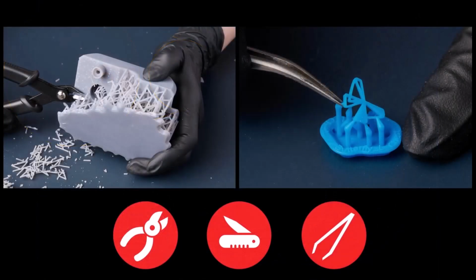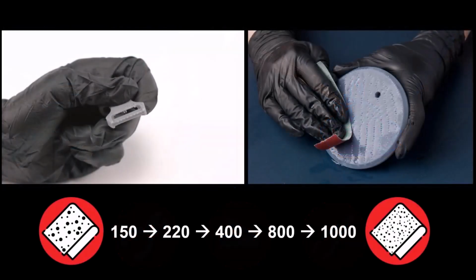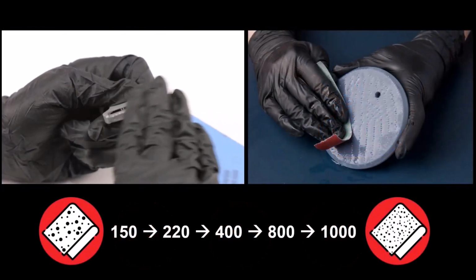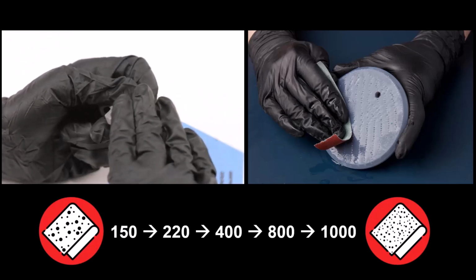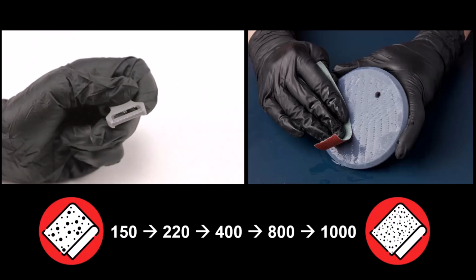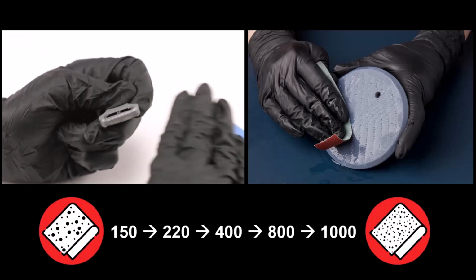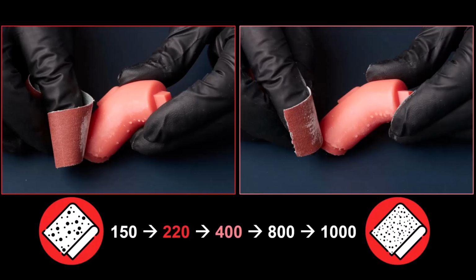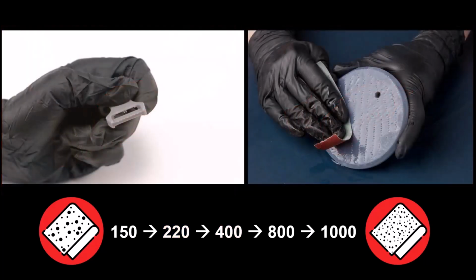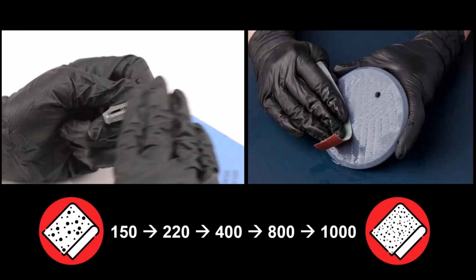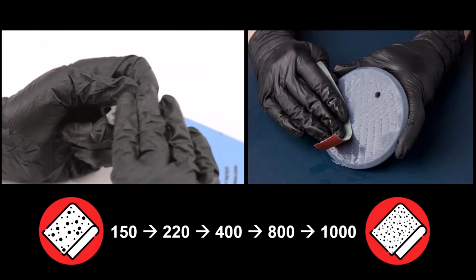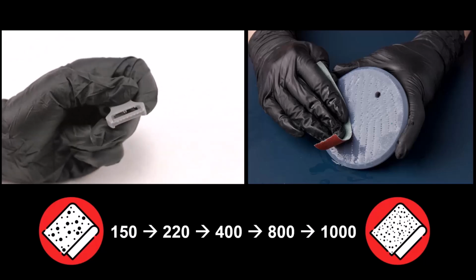Well, for starters, flush cutters, hobby knives, and tweezers all work really well to remove as much of the support as possible. Then it's just a matter of sanding, and as is typical with sanding, we want to start from coarser sandpapers like 150 and gradually work our way up to finer grit sandpapers like 1,000 and up. And you can see here the part is already looking a lot better. And you can also wet sand SLA parts, which helps keep the dust levels down. You just need to use things like mineral oil or water as the wet medium.